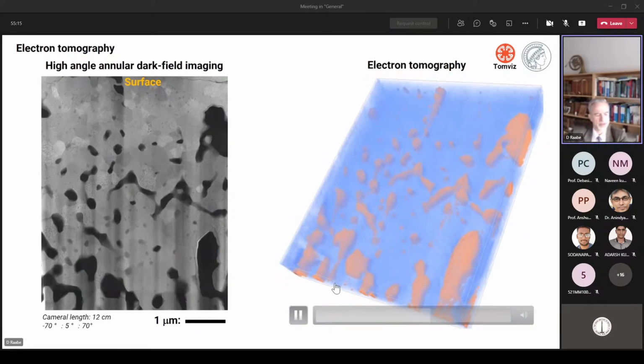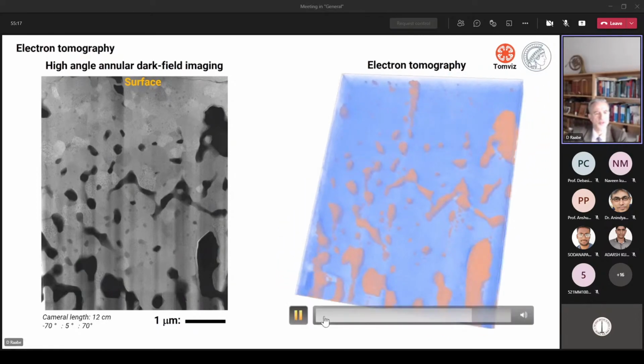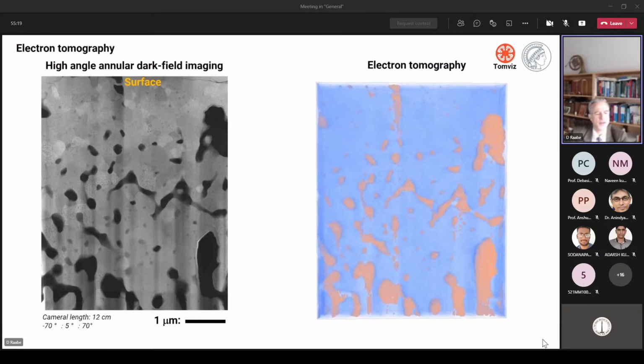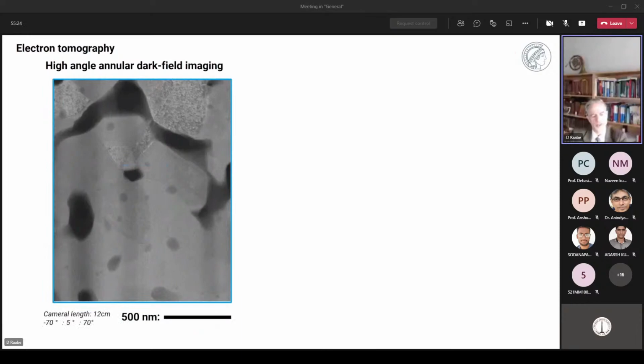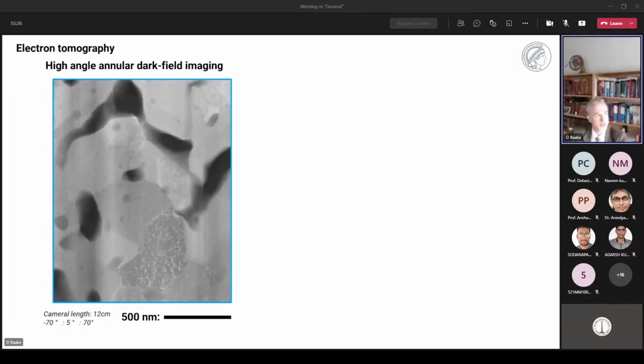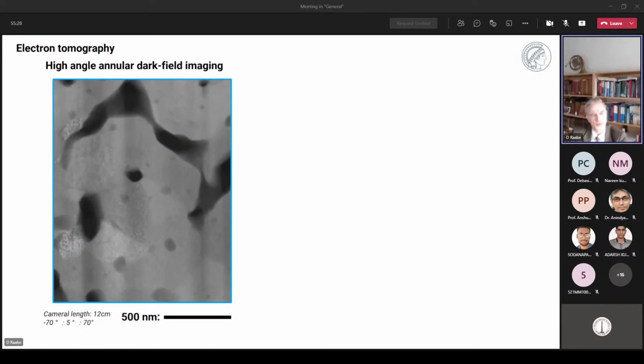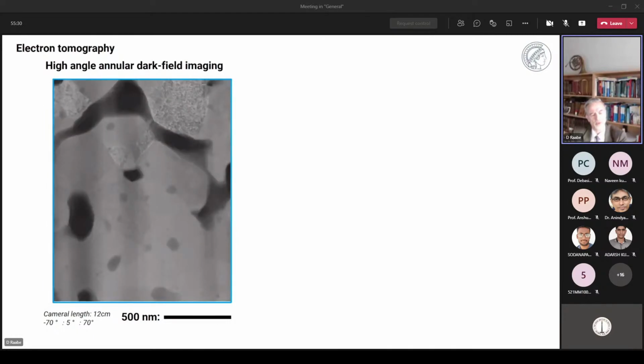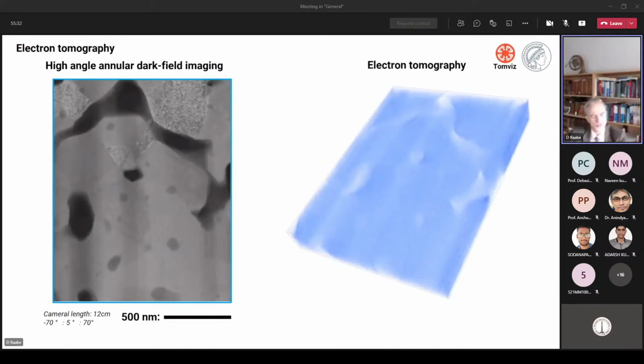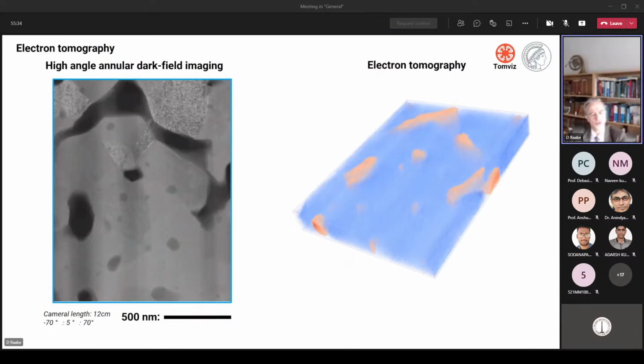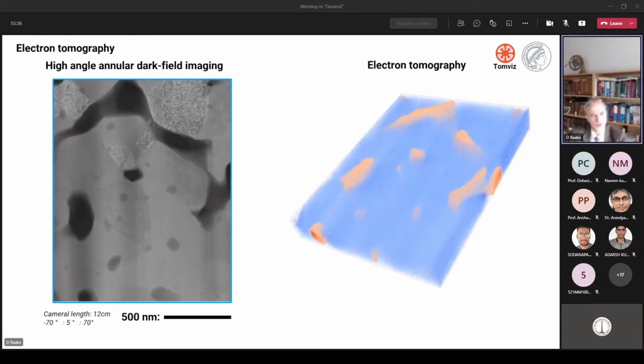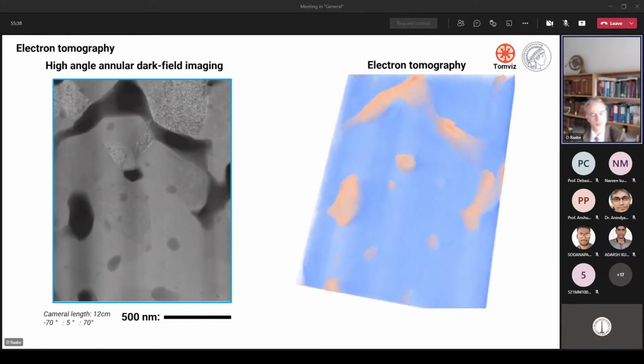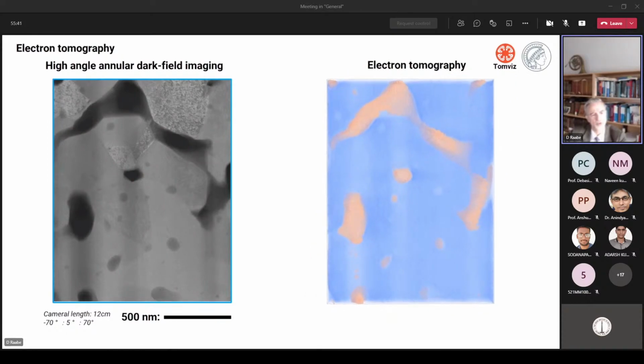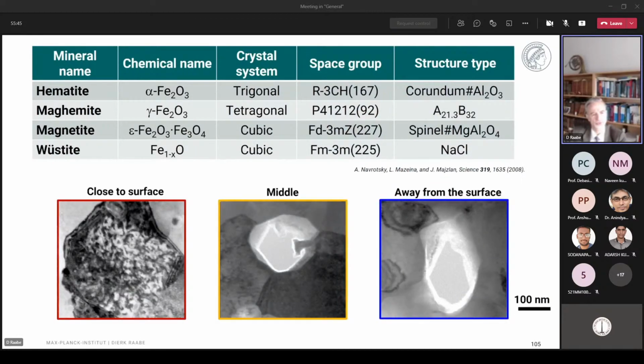And our special interest was here addressing the question on the percolation and topology of these pores that you see, particularly those that form and those that are inherited from the sintering. And we want to understand what their role is for the kinetics and for the capturing of the water of the reaction product, because one of the biggest problems is how to bring the water out of the pellet and of the shaft furnace.